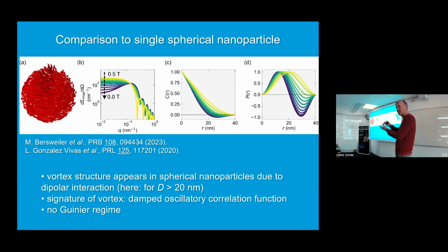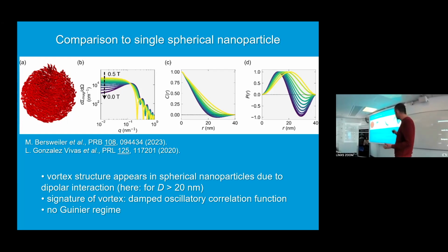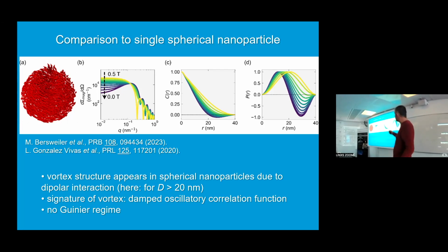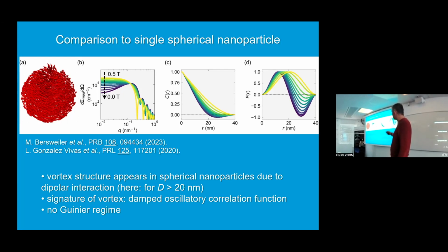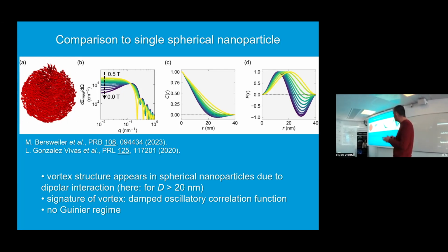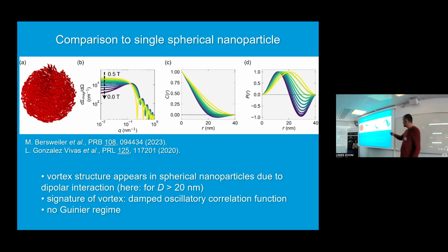Initially, when they lie on top of each other, you have the maximum of the correlation, maximum overlap. Then you shift one with respect to the other, and you get a decay of the correlations. At some particular distance R, in one region the spin points in one direction, and the other points in the antiparallel direction. That's the reason why you get a zero here, which is more pronounced here.